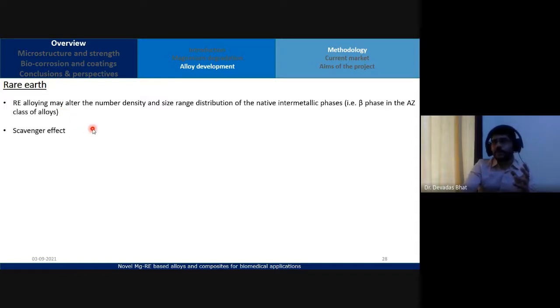It will also lead to what is called as scavenger effect. Okay, so what is this scavenger effect? This rare earth, when you introduce it into your alloying, it will interact with the impurity elements in the alloy. Okay, and whatever adverse effects those impurity elements would provide to your material, the rare earth will make sure that the interaction between this rare earth with the impurity elements will not have any direct influence on the bulk corrosion.